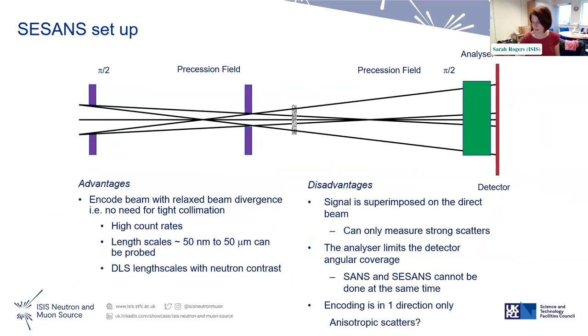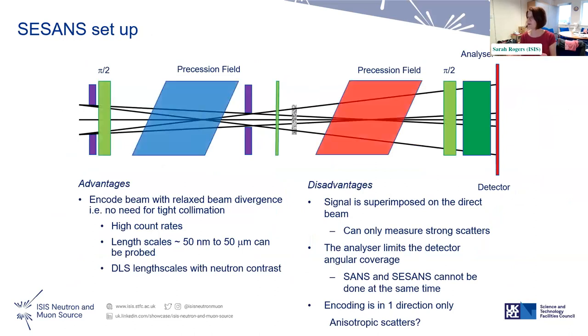So if you think about a SANS instrument as we had before, and then you stick the SESANS part of it on, you can basically have the shorter instruments, but then probe the low Q end of things without having to push to these very long low flux instruments. So the advantages of spin echo SANS is that it allows you to encode the beam with this sort of relaxed divergence that we talked about with no tight collimation. It has high count rates and it can probe really big length scales, so sort of 50 nanometers up to the micron length scale. So it's basically like dynamic light scattering length scales, but with neutron contrast.